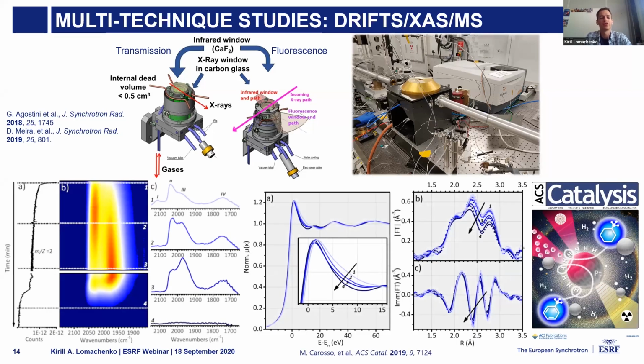This approach is actually very fruitful, as illustrated, for example, by this study made by the group led by Professor Elena Groppo from Turin. Here the focus was on the structure and interaction of platinum nanoparticles with hydrogen, so the formation of platinum hydride. Infrared was used to monitor the hydrides themselves, while XAS was used to probe the structure of platinum nanoparticles.